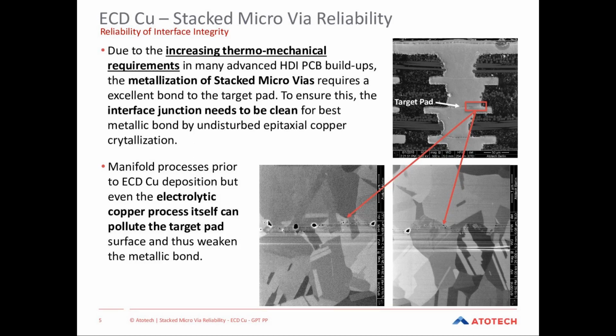And here it was found that the interface reliability is quite often disturbed by any pollution, by any kind of contamination, or it is disturbed by microvoiding. These are the two main reasons found to be responsible that the microvia integrity is not good enough, that the thermomechanical stress can lead to separations and finally to a failing of the build-up in the field.